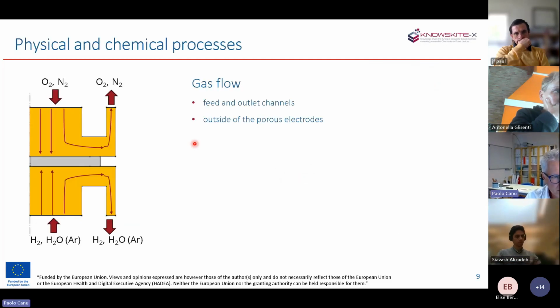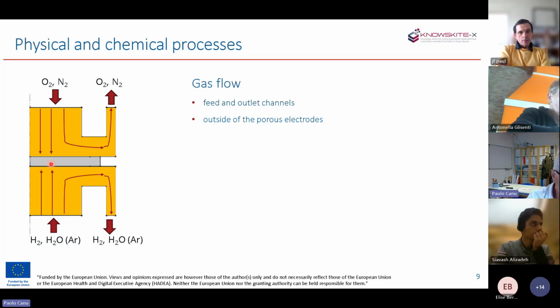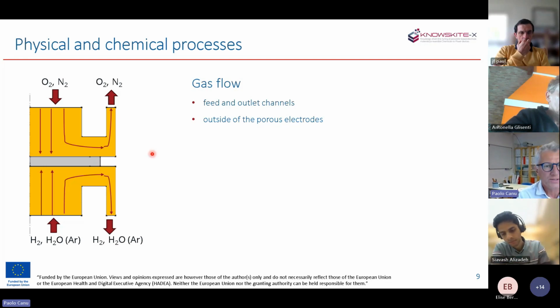Starting with the simplest part, the gas flow in the open channel means that the air will enter. Some oxygen will enter into the electrode, might react, and the residual oxygen will leave from this side. The same description occurs on the anode side, where a stream of gases enter and leave continuously, let's say, wet the surface of the electrode, providing the fuel at the bottom and the oxygen on the cathode side so that the electrode can work.